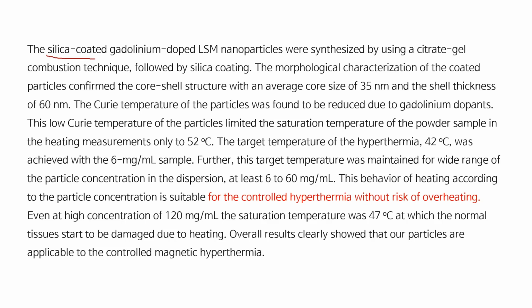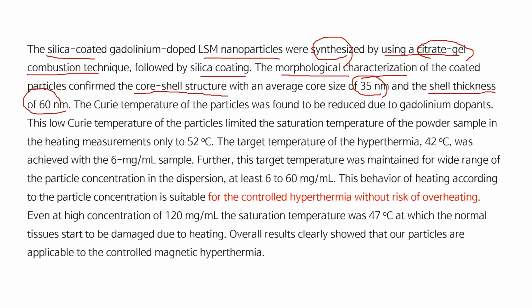The silica-coated gadolinium-doped LSM nanoparticles were synthesized by using the citrate gel combustion technique followed by silica coating. The morphological characterization of the coated particles confirmed the core shell structure with an average core size of 35 nanometer and a shell thickness of 60 nanometer. We showed the TEM images before. The Curie temperature of the particles was found to be reduced due to gadolinium dopants.